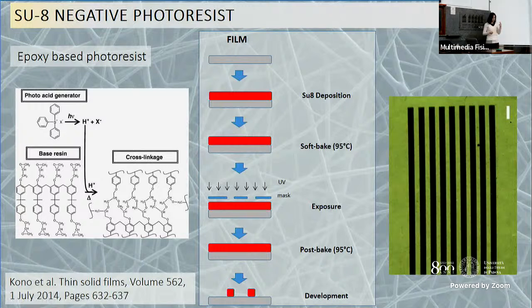The key elements are two: exposure to UV light and temperature. When you expose the material to UV light, you activate the photoacid generator. And when you exceed some temperature by heating the material, you enhance the cross-linking of the material. So the final result is that the regions of the material which are exposed to UV light undergo a process of cross-linking. So they become a very stable surface.